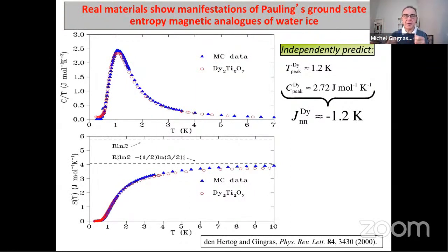It has a long range nature, and everything that I explained from the beginning of the talk up to this point always involves the notion of simplicity of the Hamiltonian to allow a large flexibility to have extensively degenerate ground states. But dipolar interactions just do not have that quality. They are extremely constraining on the ground state. Yet empirically, we found that these dipolar interactions explain 95% of the physics, if one can speak like that, of all these materials. And not only dysprosium titanate, but all dysprosium and holmium-based spin ice, either with titanium, tin, germanium, or zirconium. So what's going on?